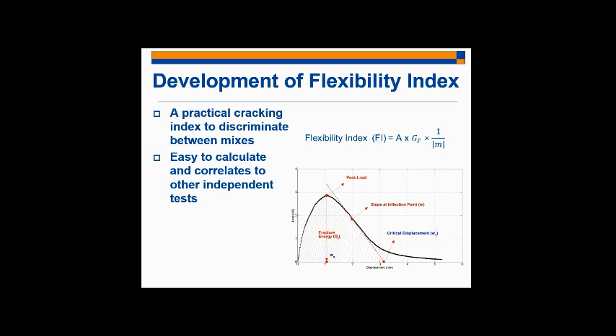But there are other parameters that you can extract that I mentioned earlier, such as the peak load, or the slope at the inflection point, or even the critical displacements. And so what we found to be most effective and most in line with engineering intuition, preliminary prediction of field performance, and also independent tests, was this combination of the fracture energy and the slope. So this slope here, the slope of the line fit through the first inflection point past the peak load.